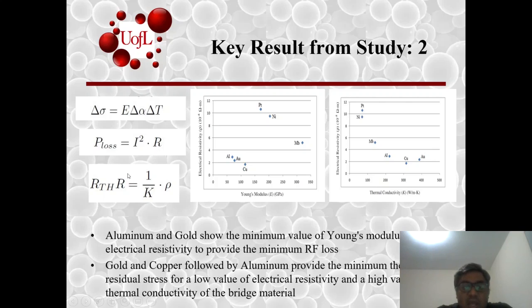And they have shown that the multiplication of the thermal resistance and the electric resistance is equal to the electric resistivity divided by thermal conductivity. So based on this equation, they said that they were looking for that material for which the electric resistivity is low and the thermal conductivity is high. And for this, at first they plotted the electric resistivity versus Young's modulus.